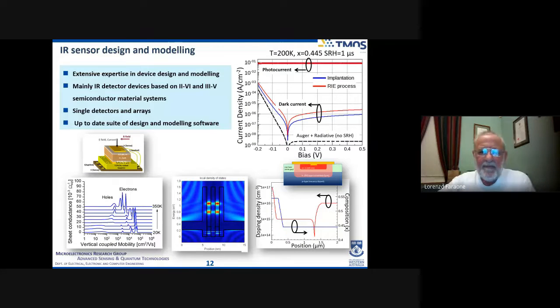So, I'm not going to spend too much time on the details of device modeling and simulation, but it does require some fairly good modeling capabilities to design the detectors, because you can vary the doping in the material as a function of position as you grow the layer, and you can vary the composition, going back to the ratio of mercury to cadmium. You do that in order to grow a wide bandgap layer at the back of the substrate, at the back of the epitaxial layer, as well as at the surface, in order to minimize surface recombination, for example, just to give you one example.